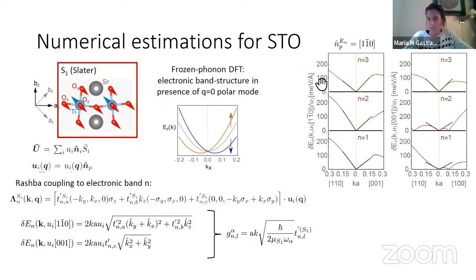This is some example of how Ab-initio looks. So I'm already plotting here the difference between up and down along different momentum directions, normalized with respect to this U. We do this for different U values, and we make sure that when you plot this, this quantity is not changing, so that you are in the linear regime. Because of course you can also get higher order terms. Numerically, you can go to U squared, U cubed, and so on. So you have to make sure that what you're extracting is the linear form. So that's how we do it.